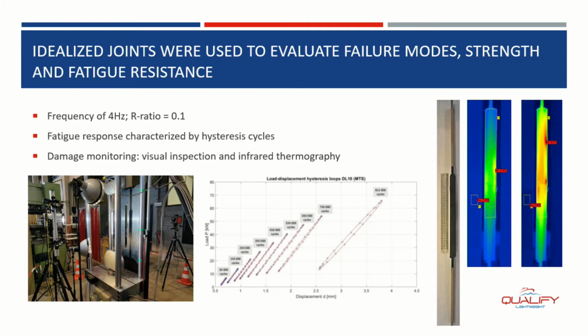with infrared thermography. At the bottom left, you see a photograph of the tensile test setup, and I just added this to the slide to show you that we try to follow quite a lot of the mechanical behavior. At the left, there are 2 cameras installed for digital image correlation to follow the strains in the adhesive. At the back, there is an infrared thermographic camera to follow the damage evolution. We also had visual inspection and tried to see what happened with damage evolution during the fatigue testing.